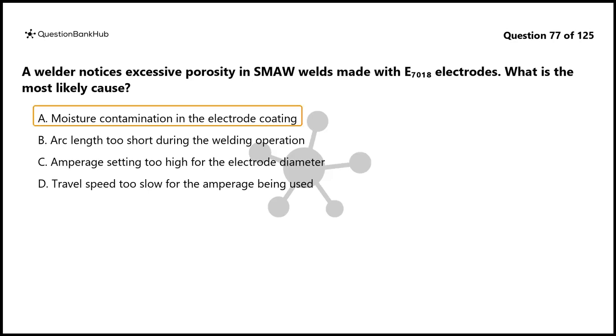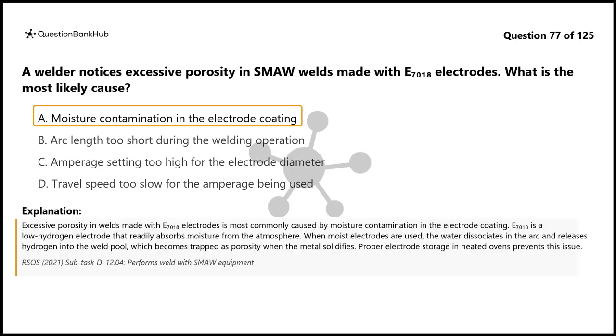The correct answer is A. Moisture contamination in the electrode coating. Excessive porosity in welds made with E7018 electrodes is most commonly caused by moisture contamination in the electrode coating. E7018 is a low hydrogen electrode that readily absorbs moisture from the atmosphere. When moist electrodes are used, the water dissociates in the arc and releases hydrogen into the weld pool, which becomes trapped as porosity when the metal solidifies. Proper electrode storage in heated ovens prevents this issue.